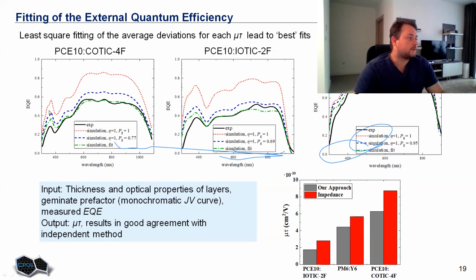So the black curve here for each device system which we use stands for the experimentally measured EQE. The red dashed line stands for the theoretical maximum EQE, which we would get if we didn't have any losses from recombination and extraction. Once we take into account the geminate recombination prefactor, PG, its actual value, we already reduce this external quantum efficiency, and this stands for the blue dashed line. Then we apply fitting of our theoretically calculated curve to the experimental one in order to get the best fit and extract at which value of mu tau product we get the best fitting between experiment and simulation.